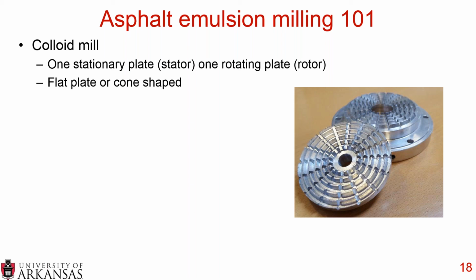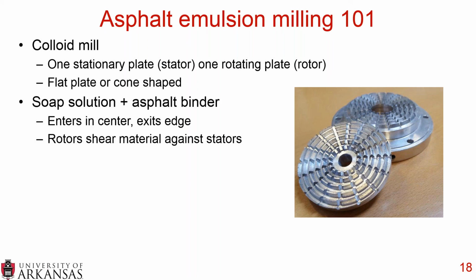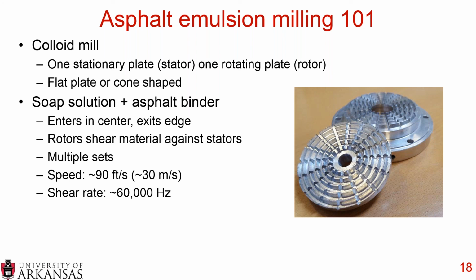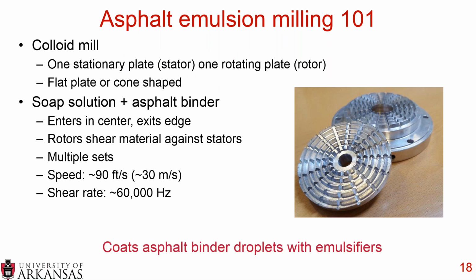And this can either be a flat plate, which is shown in the picture, or it can be a cone shaped. And if you close your eyes and think of a cone, that's exactly what it looks like. It's two cones that slide into each other, but they have these type of teeth on them to help with that breaking down. So the soap solution in the asphalt binder enters in the center and it exits on the edge, as I mentioned, and the rotors shear the material against the stators, and there are multiple sets of these, and they're going at about 90 feet per second. And this is a shear rate of about 60,000 hertz. So this is an incredibly fast speed, and these plates are fractions of an inch apart. It's very, very close together. And so this is what shears the asphalt binder droplets into small particles, and you get your asphalt emulsion. And as it's going through these rotors and stators, that is what forces the emulsifiers out of the soap solution into the asphalt binder droplets.